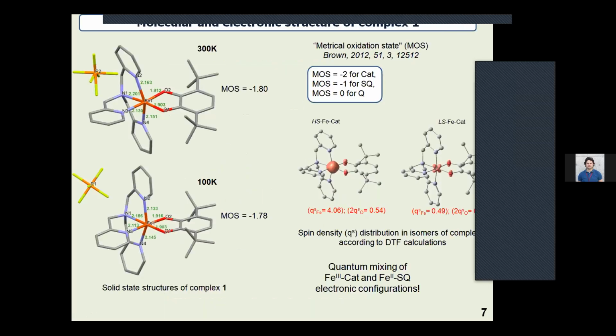According to X-ray diffraction analysis, complex 1 was found to be unsolvated, while complexes 3 and 4 contain a half of solvate water molecule. The metal center in all six-coordinate iron complexes possesses distorted octahedral geometry composed by 4 nitrogen atoms of TPA ligand and 2 oxygens of catecholate. The molecular structures were determined at 2 temperatures.